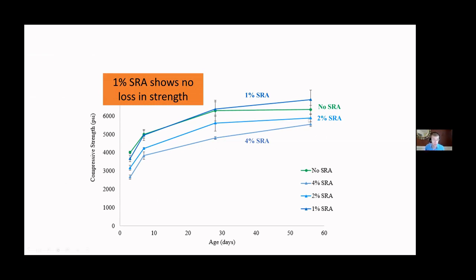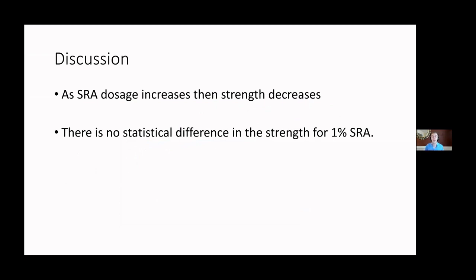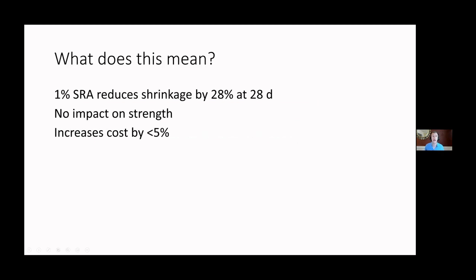At 2%, we lose, and at 4%, we lose even more. Side effects. We don't want side effects. 1%, though, shows some promise. So as SRA dosage increases, the strength decreases, but there's no statistical difference in the strength at a 1% SRA dosage. And so what does this mean?